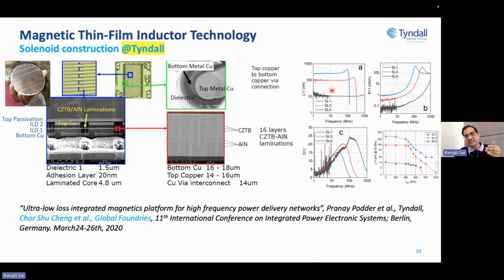If you see the Q factor of this, the red one, which has 100 permeability, has a Q factor of 20. This is device Q, this is not the material Q only. So this incorporates the copper turn and the losses related to the copper turn as well. So the material quality factor is much higher than 20. Overall, this is a fantastic demonstration of a very high frequency inductor.